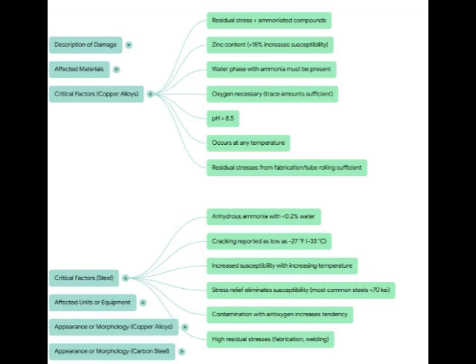Trace amounts, wow. And the stress needed. For these, say, heat exchanger tubes, does it need a big operational upset, or is just putting the tube in place enough? Often, just putting it in place is enough. The cracking can happen at pretty much any temperature common in these systems. It's not usually about high operational loads. Think about when you roll a tube into a tube sheet in a heat exchanger. That process leaves residual stress, hoop stress, in the end of the tube. That built-in stress is often all it takes for SCC to start once the chemistry is right.